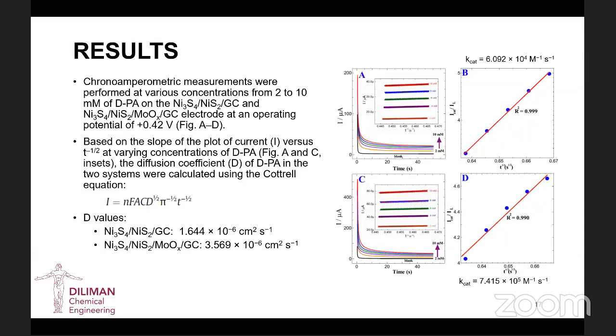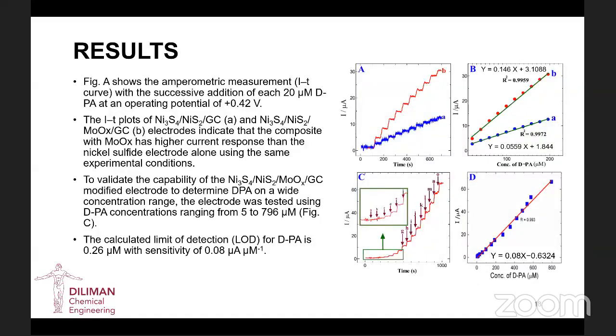So chronoamperometric measurements were also performed at various concentrations to determine the operating range of the material. And based on the slope of the plot, we were able to calculate the diffusion coefficients, which are given below. And we also did additional amperometric measurements where we added 20 micromolar DPA at various intervals. And using this information, we were able to calculate the limit of detection, which was given in figure D. So anyway, these studies are conducted to determine the range of the concentration, and then to determine the LOD and the sensitivity, which are given in the slide.